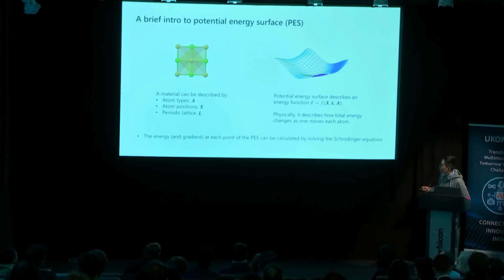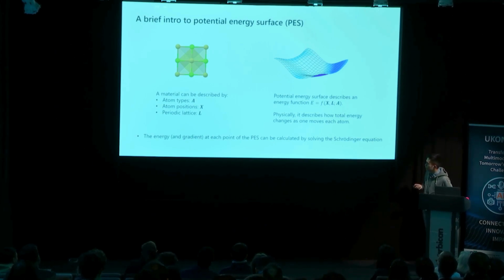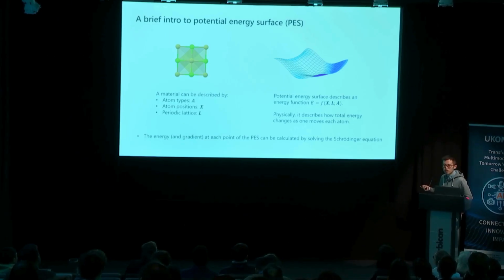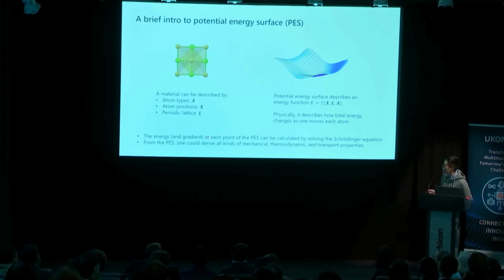The good thing is that you can actually compute the energy and the gradient of this potential energy surface at every single point by solving the Schrödinger equation. This is quite expensive, but if you have a lot of compute, you can actually do that. So this creates a way that you can generate almost infinite data to learn this potential energy surface. And the second good thing is that once you know the potential energy surface, one could derive all kinds of materials properties, including mechanical, thermodynamic, and transport properties. Because what these properties are basically about is how each atom moves inside these materials.